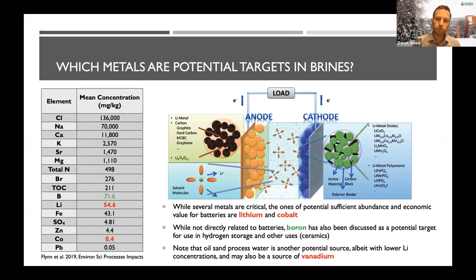So, just a little bit of a general topic here: which metals are potential targets in brines? On the left-hand side is an analysis of a typical brine in Alberta, from the Duvernay formation. One of the issues we're dealing with in this resource is that it's got a ton of sodium and chloride: 136,000 ppm chloride, 70,000 ppm sodium. That's about 200,000. Keep in mind the salinity of the oceans is around 35,000 ppm.